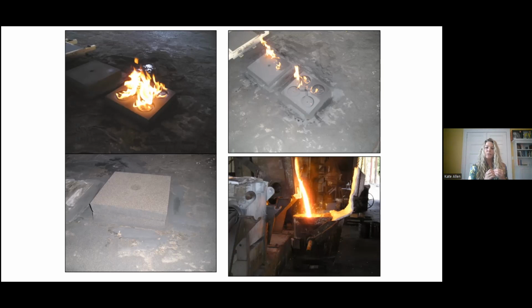Typically, a casting will solidify in about 5 minutes, and it comes out of the mold in about a half an hour. But larger castings, they may sit up for 24 hours. It just really depends on the size. And the desired cooling is always based off wall thickness. So we typically pour castings somewhere between 3/8 of an inch and an inch.